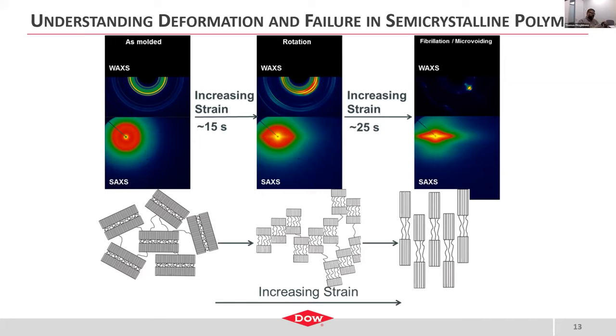However, if you take that material and place it in an Instron and start to pull it apart and stretch it, what you start to see in the wide-angle X-ray scattering is more preferred orientation along that axis, with the intensity of your X-ray scattering increasing preferentially in one direction and decreasing in the other. You also see in the small-angle scattering evidence of lamellar rotation, where you start to see orientation and changes in intensity as a function of azimuthal angle as you integrate around the scattering curve, corresponding to the lamellar rotation and interlamellar distance.